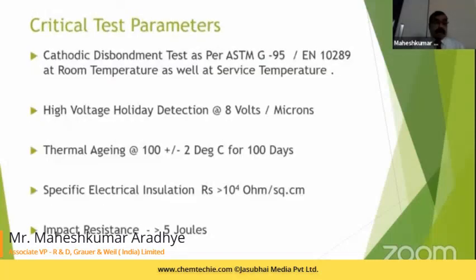Another critical parameter is the cathodic disbondment test, which is to be carried out at the service temperature. It is not only at room temperature, but also at the service temperature. As I already discussed, high voltage holiday detection at 8 volts per micron. The thermal aging cycle is at 100 degrees plus or minus 2 degrees centigrade for 100 days. The electrical insulation, where they are talking about the surface resistance, should always be greater than 10 to the power 4 ohms per square centimeter, which is very, very high.